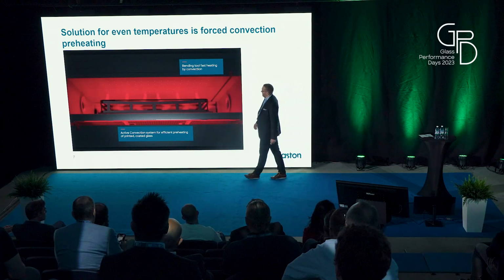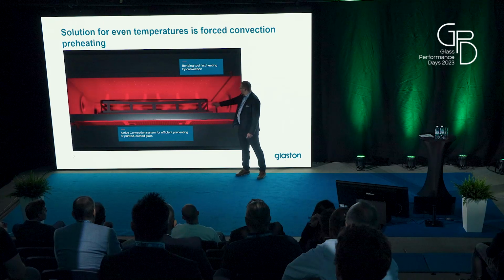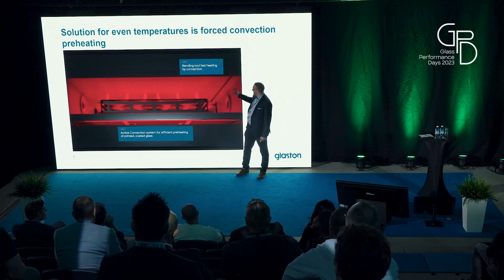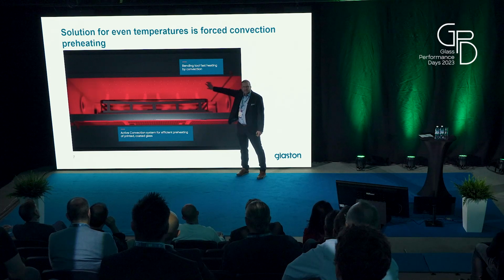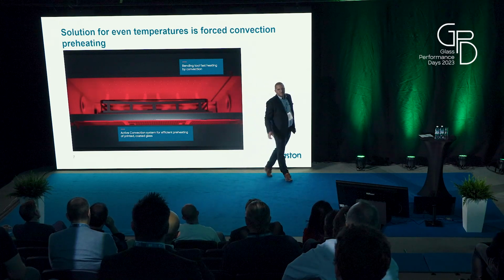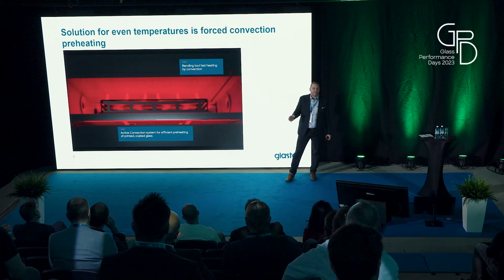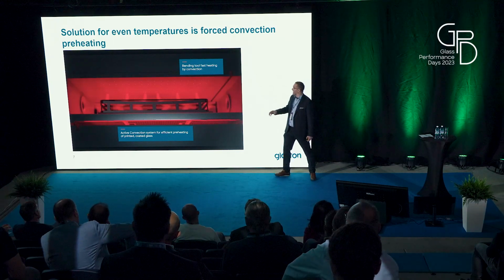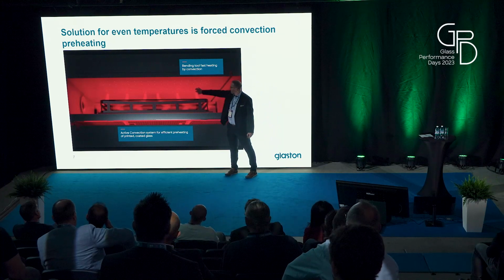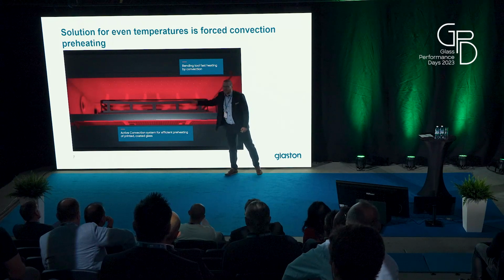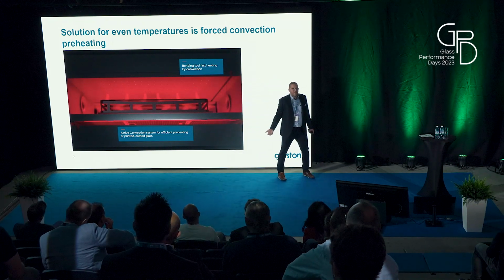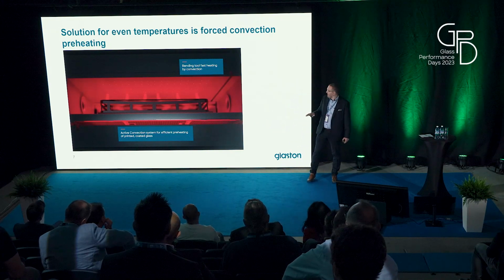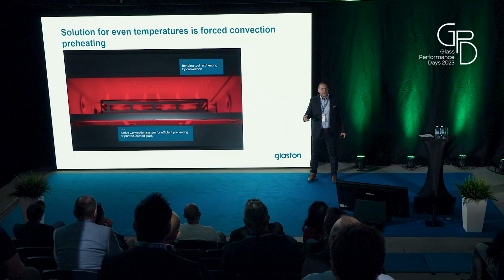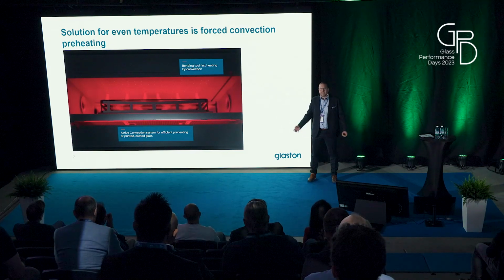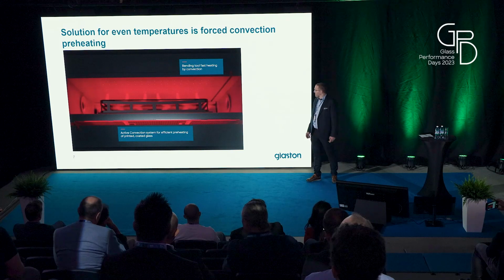And at the same time, air is going to a blower, and it's circulated to an air channel, which is going through where these heaters are. This air is heated, and then when it's coming out from the hose, which we call, in this case, nozzles, then it's blown on the glass surface. And that way we can get this convection. We had to reduce the radiation a little bit, but with increased convection, we can get the benefits we want to get from this process.